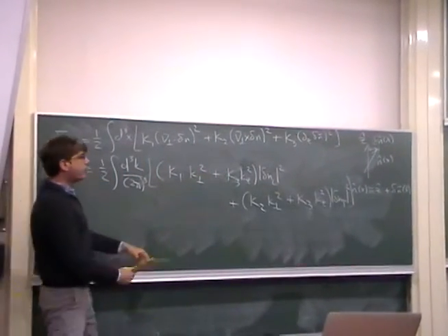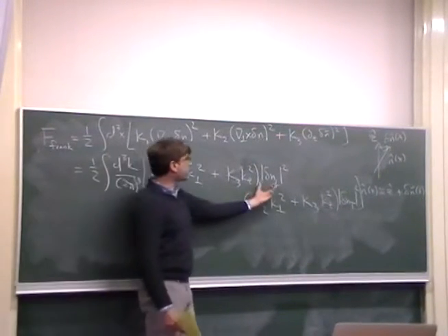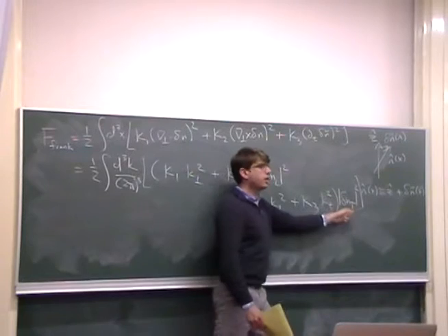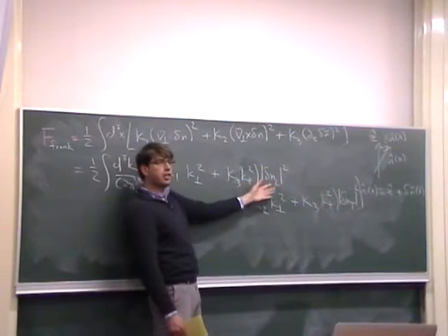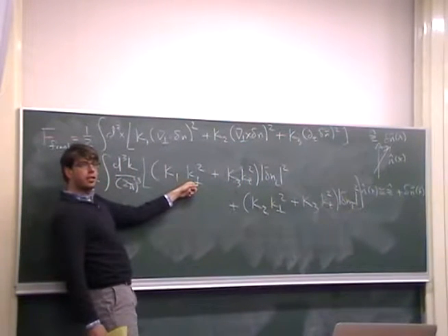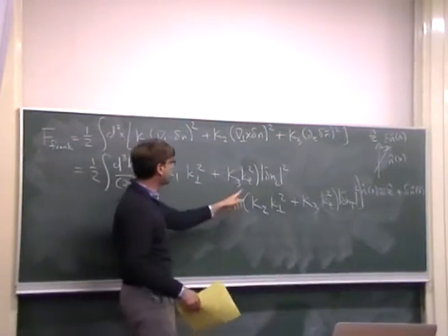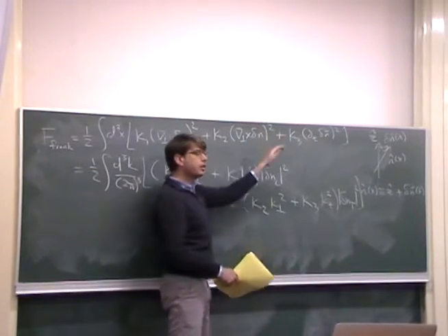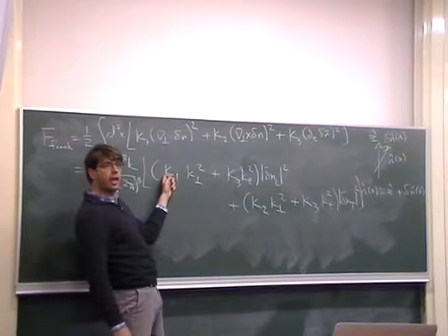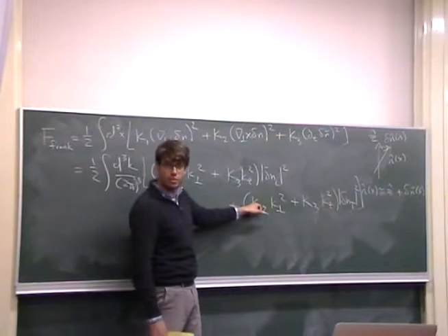So now we've made some progress, I guarantee you. What we've done is we've grouped these two polarizations into two independent modes in Fourier space. The cost for amplitude fluctuations in either the longitudinal direction or the transverse direction simply depends on the magnitude of the wave vector in the plane perpendicular to the nematic orientation or along the direction of the nematic orientation. And we see now that the costs for longitudinal fluctuations depend on splay, but not twist, and the costs of the transverse fluctuations depend on twist, but not splay.